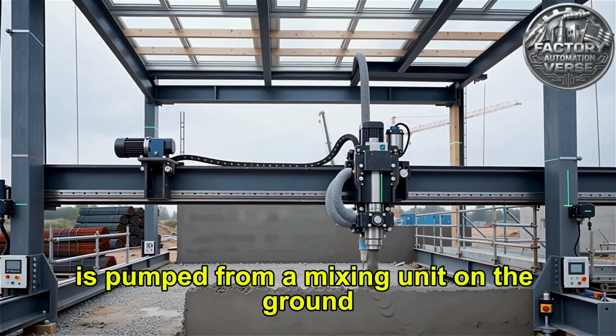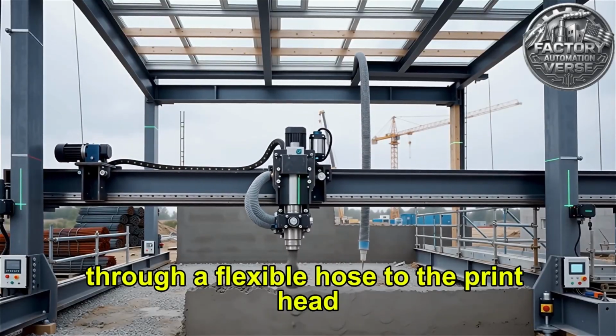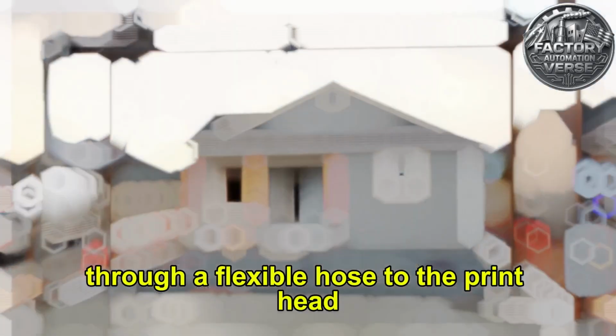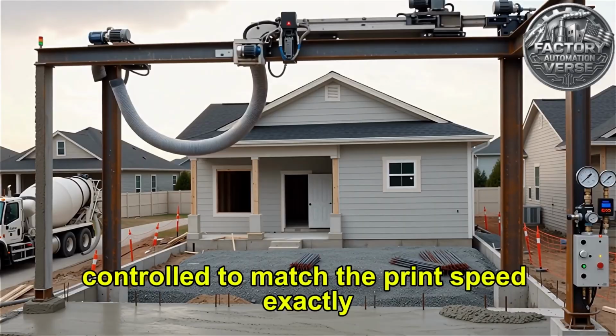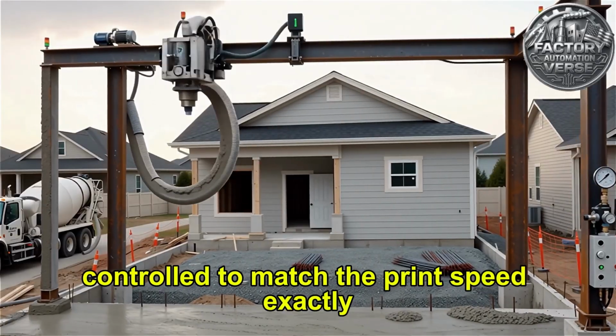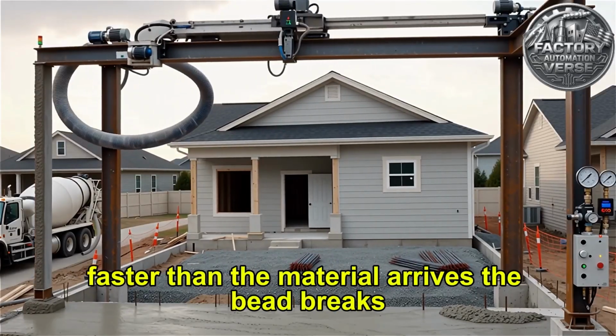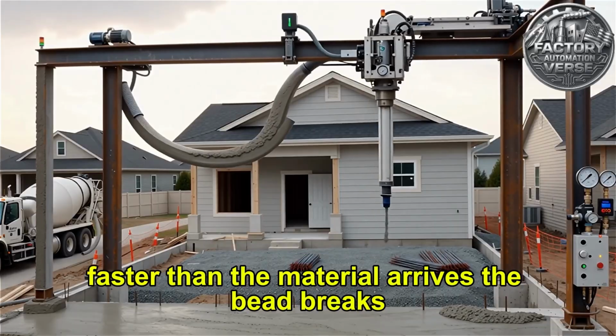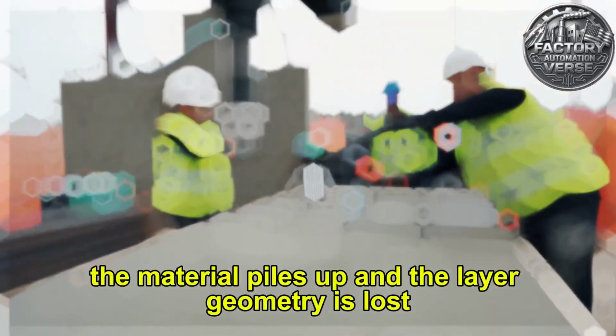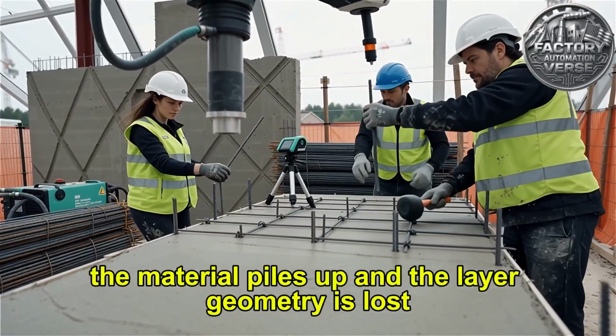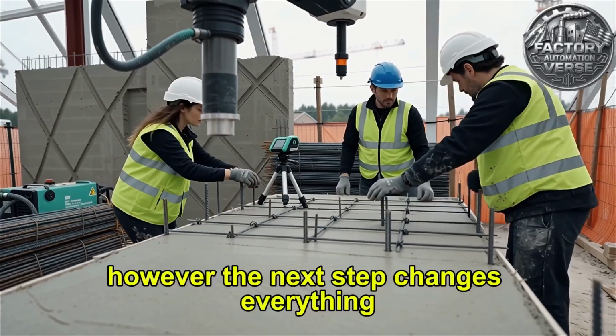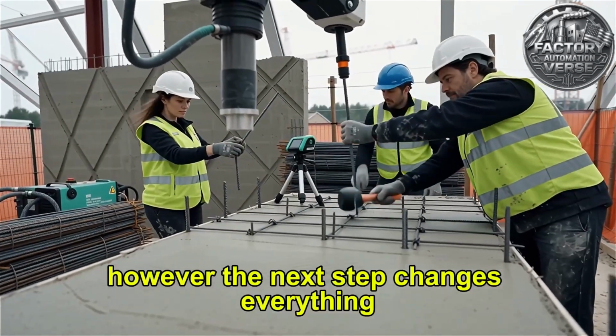The concrete is pumped from a mixing unit on the ground through a flexible hose to the print head, with the pump pressure and flow rate controlled to match the print speed exactly, because if the head moves faster than the material arrives, the bead breaks. If it moves slower, the material piles up and the layer geometry is lost. However, the next step changes everything.